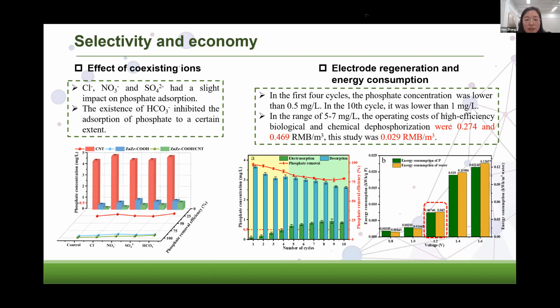In order to evaluate the stability of the composite electrode, we carried out 10 adsorption-release experiments. The results show that in the first four cycles, the phosphate concentration was lower than 0.5 milligram per liter. And in the 10th cycle, it was less than 1 milligram per liter. Moreover, in low concentration phosphate treatment, the operating cost of this study was only 1/16 of that of chemical phosphate removal.